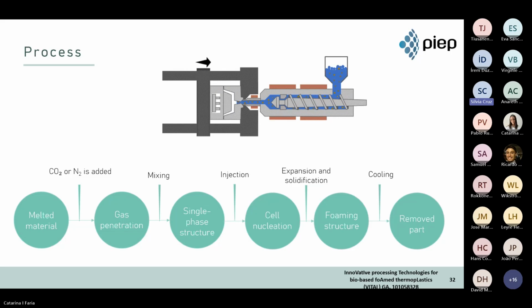So the physical foaming agent variation is accomplished by injecting the gas in its supercritical fluid phase through a dedicated supercritical fluid injector. In this phase, the gas is in a liquid-like state, obtained by maintaining the foam agent above a critical pressure and temperature, allowing the gas to quickly diffuse into the polymer melt, creating a single phase inside the barrel.